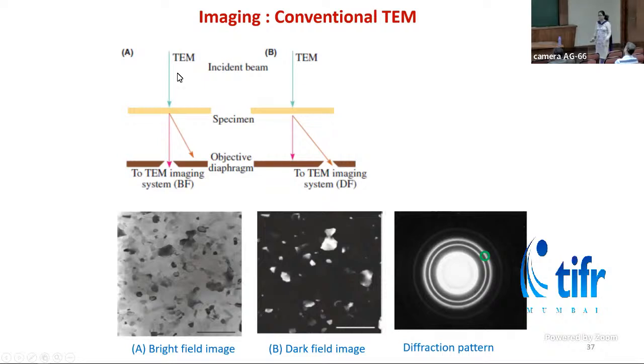Let's assume you have a sample where you have a carbon grid or carbon film. On that you have metal nanoparticles or gold nanoparticles. Then those gold nanoparticles, being thicker, will stop the electron beam, and hence those will look a little dark in the image. That is called mass thickness contrast. Again, gold being high Z number will absorb the electrons, hence they will look dark in the sample. If the gold particle is crystalline in nature, it has lattice planes which will diffract the electron beam, and hence it will have a diffraction contrast also.